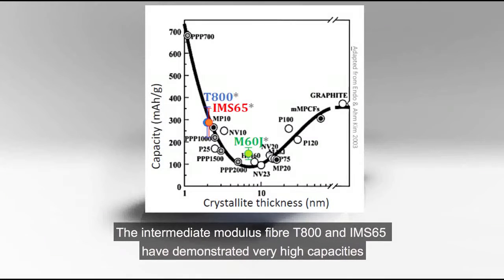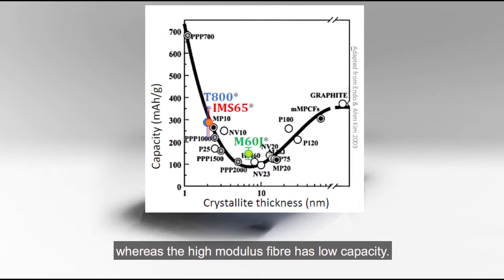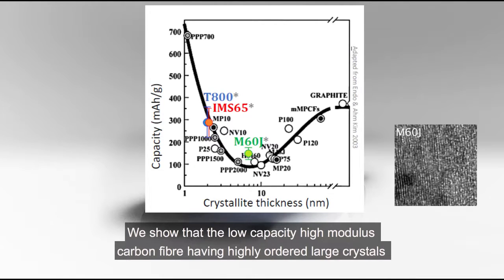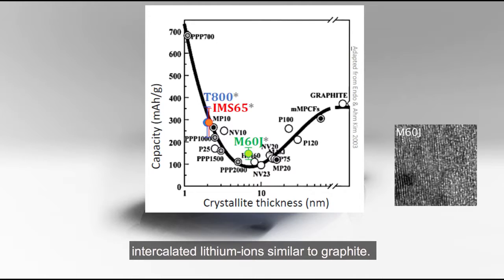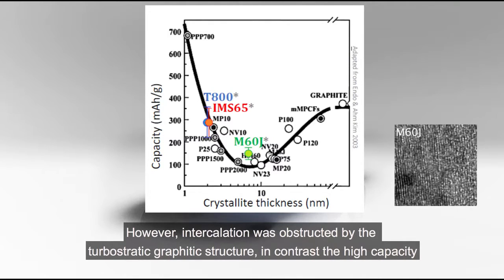The intermediate modulus fibers T800 and IMS65 have demonstrated very high capacities, whereas the high modulus fiber has low capacity. We show that the low capacity high modulus carbon fiber, having highly ordered large crystals, intercalates lithium ions similar to graphite. However, intercalation was obstructed by the turbostratic graphitic structure.